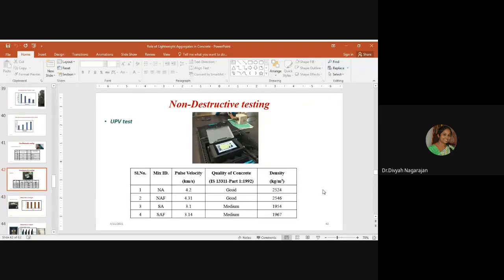Coming to the UPV test, the UPV test is also an indicator of the quality of concrete. The density of the concrete can be determined through the pulse velocity. Owing to the porous nature, the lightweight aggregate concrete had a medium quality, and the density is lower when compared to the normal aggregate concrete, and the pulse velocity is considerably lower when compared to the normal aggregate concrete.